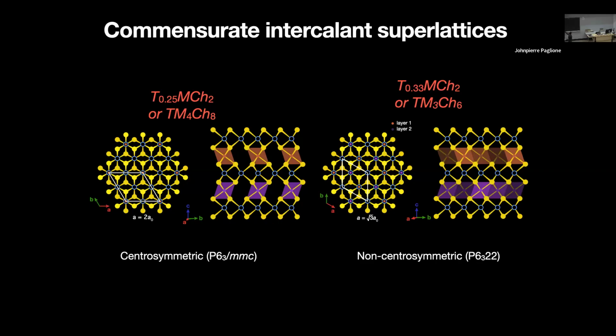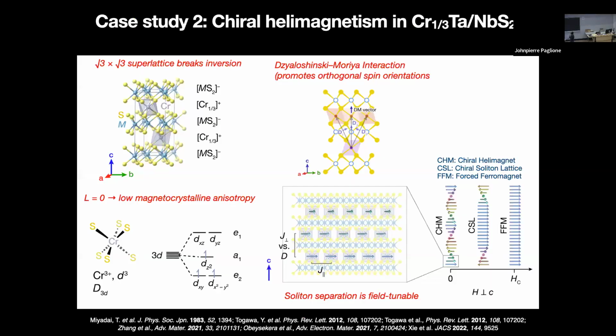Okay, so these are the two commensurate superlattice structures, and as I will try to impress on you later on, historically we've always sort of assumed that if we made the composition 0.25 or the composition 0.33, that we had pretty much exclusively the 2x2 or the √3 by √3 superlattices, respectively. It turns out that this is not at all the case, and I'll explain a little bit more why. But these are the commensurate intercalant superlattice structures.